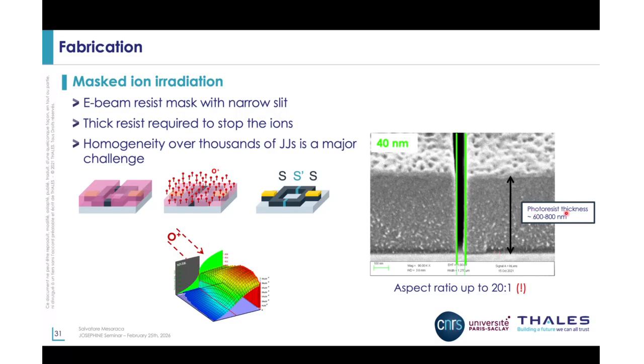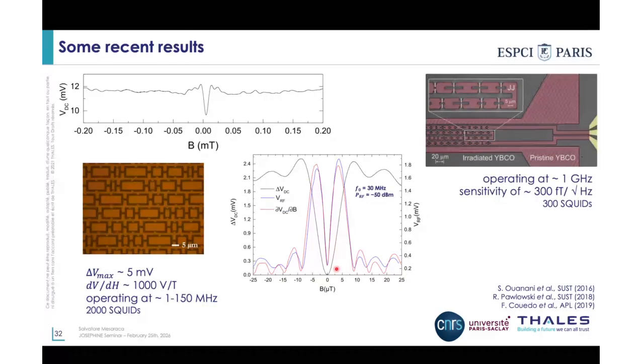Here you can see the simulation where we show actually that the thick resist is needed because we have to protect the rest of the YBCO. If we want the junctions only to be local, on these light blue areas, we have to protect the rest of it. And protect means that the oxygen ions do not have to impinge the rest of the YBCO, otherwise we will lower the TC also on these dark blue parts. But nevertheless, we managed to do this.